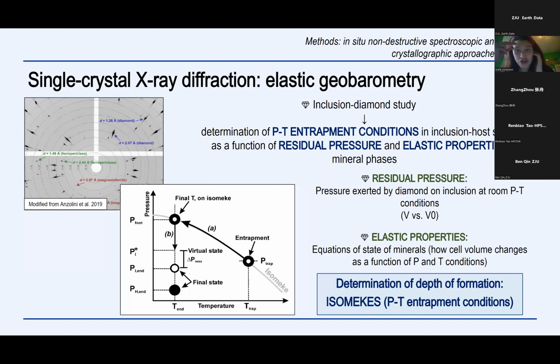The second important application of single crystal X-ray diffraction is elastic geobarometry. Elastic geobarometry is a crystallographic method that allows us to determine the pressure and temperature entrapment conditions of an inclusion-host system in general, knowing the so-called residual pressure and the elastic properties of the mineral phases that compose the inclusion-diamond system or inclusion-host systems in general.